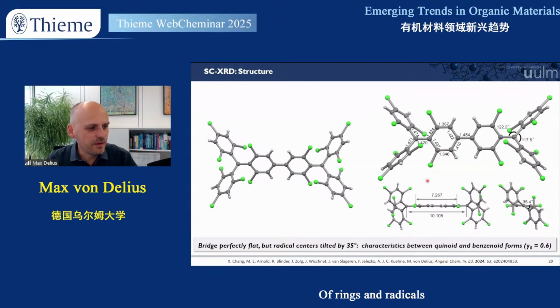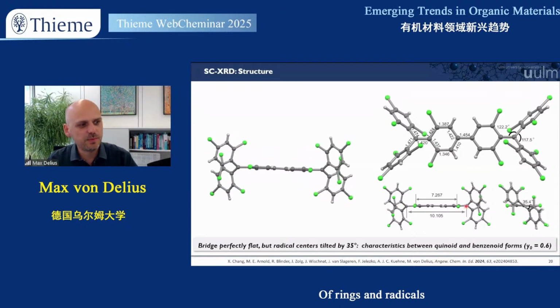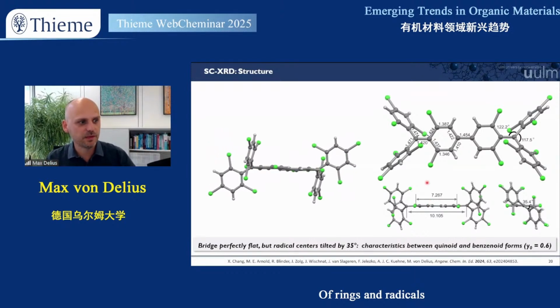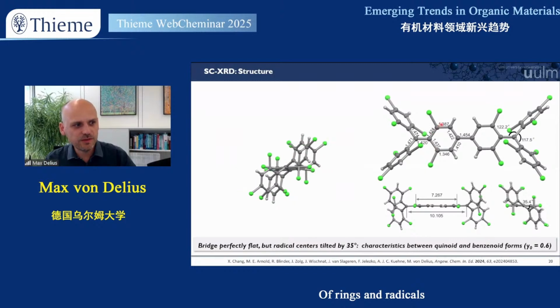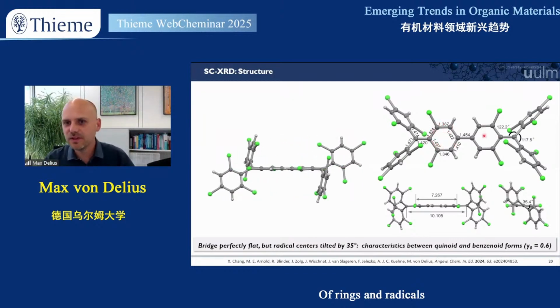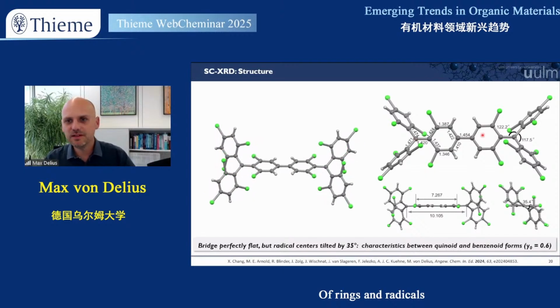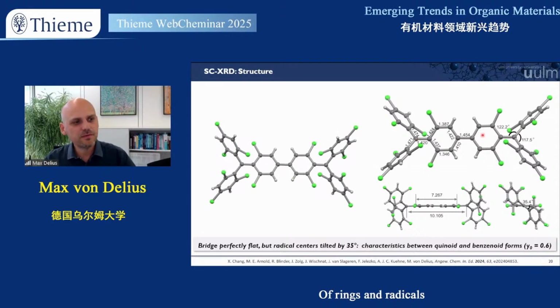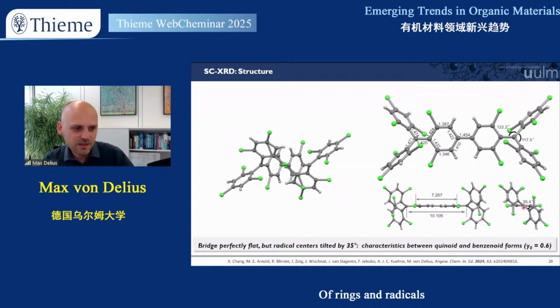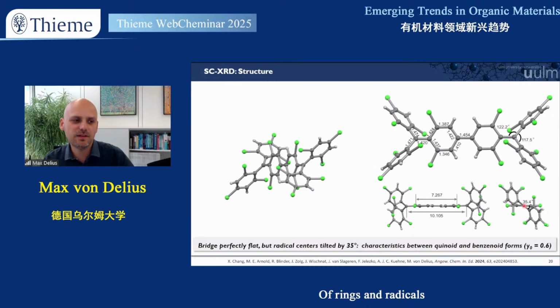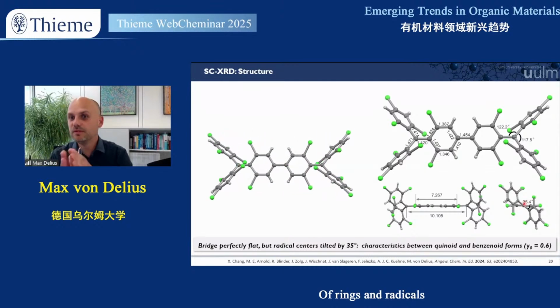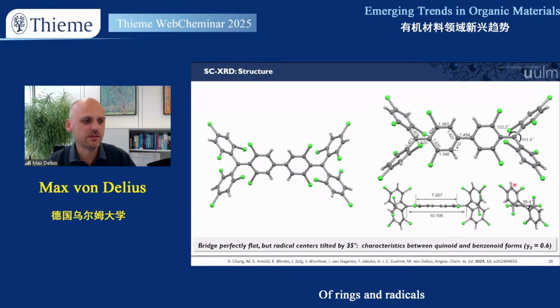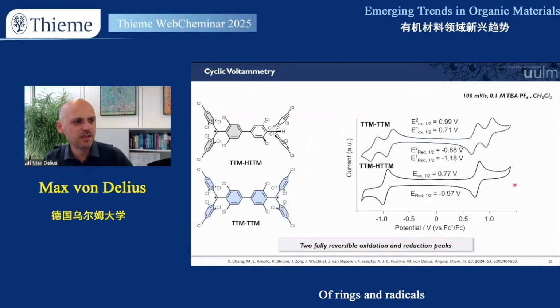So that's very, very interesting. So you have an extended conjugation path, but we don't fully fall into the boring quinoidal structure. This has probably two reasons. It's because too much aromaticity would have to be sacrificed in these two linked phenylene rings if we put them in the quinoidal form, but also the chlorine atoms tilt these carbon centers, these radical centers, by 35 degrees already somewhat out of conjugation. So there's not as much to be gained from the